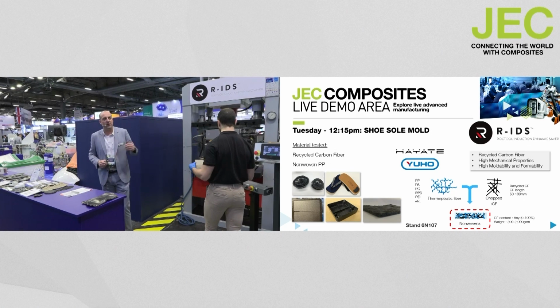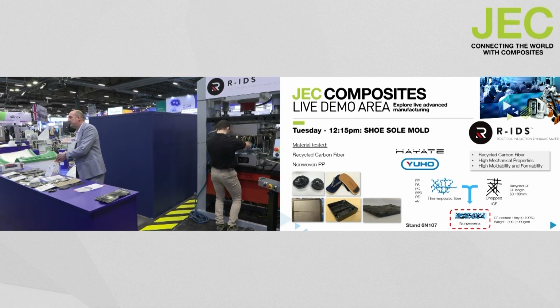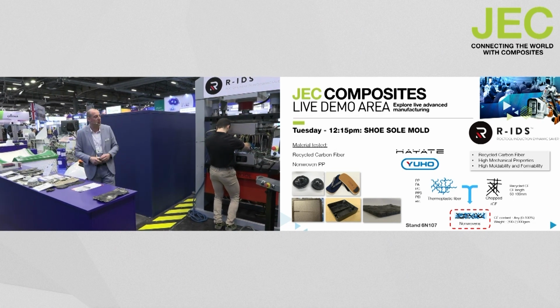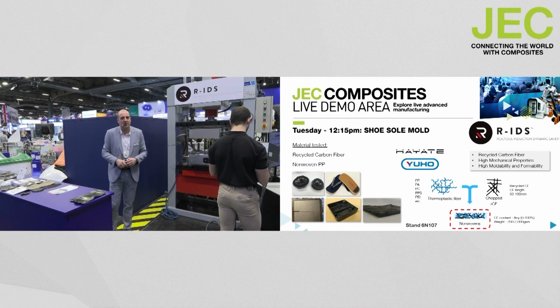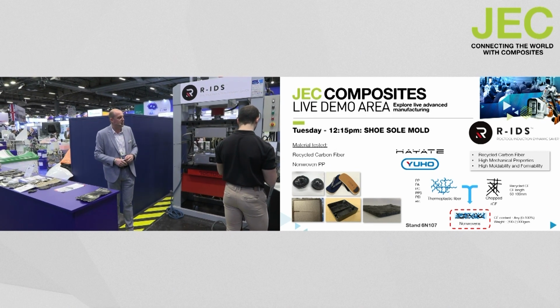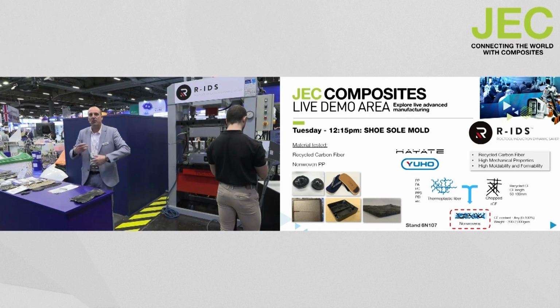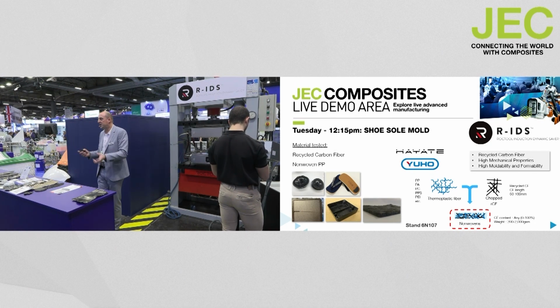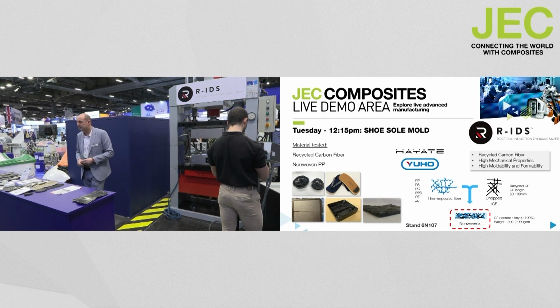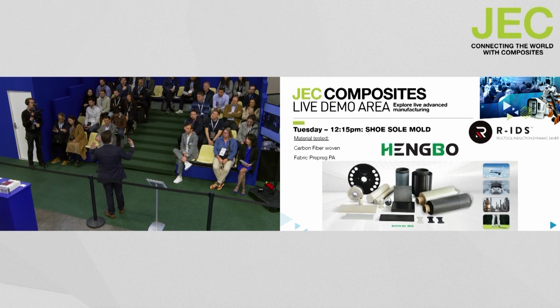So you see also the versatility of the process because we can move from polyamide resin to polypropylene, which is at low temperature. In this case, the maximum temperature concerning the transformation is around 200 degrees. And so we can, in just a few seconds, change the process parameters, we change the programming to switch to this second material. So we think of a production environment, because here I think the JEC team did a great job to recreate a production environment a little bit.